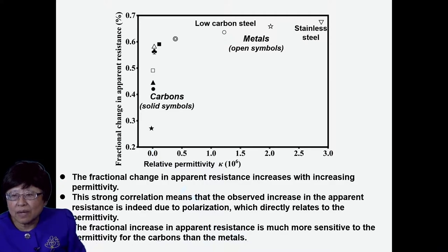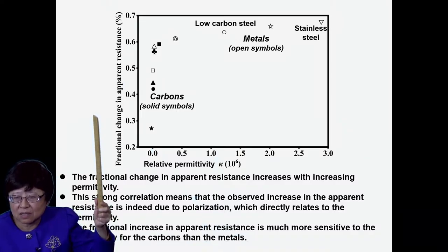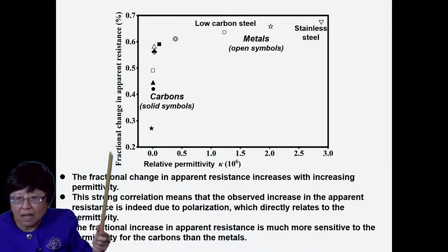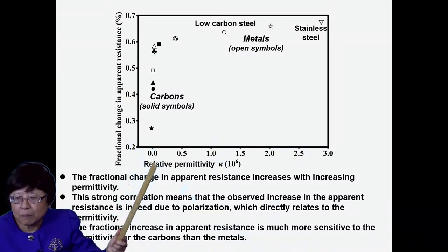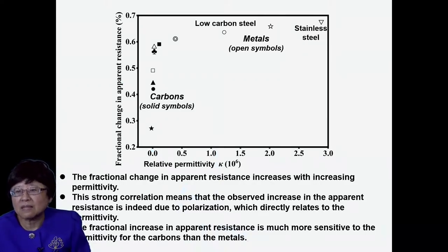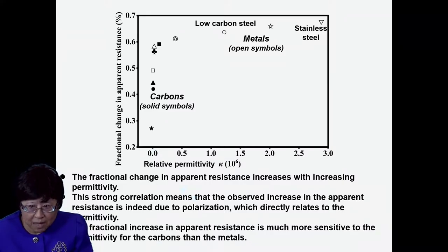Now, here shows the correlation between the relative permittivity and the fractional change in apparent resistance during DC polarization at a particular time and a particular current level, comparing various materials. And you can see a definite correlation. That is, the higher the relative permittivity, the more is the DC polarization. And that makes sense. So AC polarization, as described by the relative permittivity, and the DC polarization, as described by the fractional change in the apparent resistance, they jibe, they correlate.